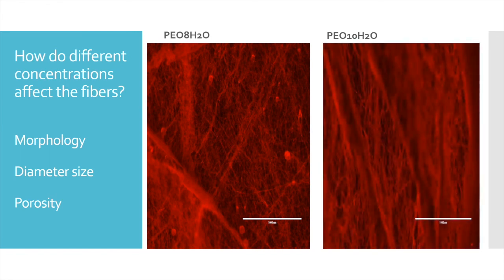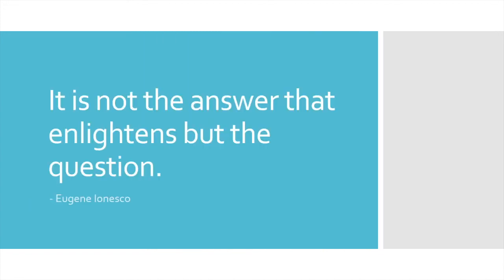So why are solution concentrations even important? Different concentration levels can affect so many things about the fibers you produce, such as its morphology, diameter, and porosity. Take a look at how a change in concentration affected these polyethylene oxide fibers. In the 8% concentration, you can see small beads of polymer, which are considered defects, whereas in the 10% concentration — the result of the first example we did — the fibers are continuously homogeneous. This goes to show that a small change of concentration can have a big effect on your fibers. It's going to take some trial and error to find out what concentration is best for the particular polymer solution that you're working with. Always remember to ask questions in the lab, for it is not the answer that enlightens, but the question. Thank you.